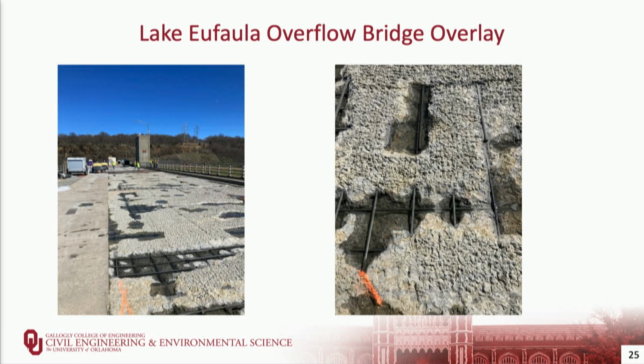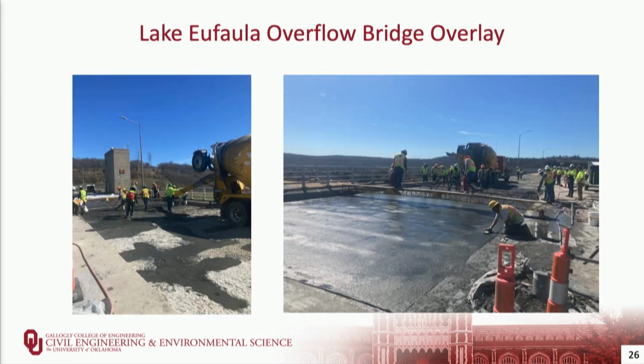One interesting thing that doesn't really have to do with connections, but is pretty exciting about UHPC from this bridge, was when they were repairing the approaches, they actually hit some of the structural rebar over the equipment galleries and had to go back with a structural overlay and decided to go with UHPC on this project. So they milled down the concrete surface, did hydrodemolition to create a nice surface preparation, and then cast an ultra-high performance concrete overlay on this project.